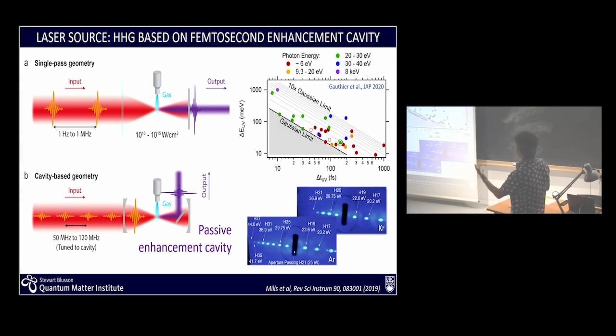The key, of course, as I said, is energy versus time resolution. Here you see a nice collection of results in a review paper from ZX Shen's group, and you see that the limit is basically the Gaussian limit, set by Heisenberg, how much you can push one versus the other. And when you go to high photon energy, so for instance in green here, 20 to 30 electron volts, you see that it's much easier to achieve the limit if you're really pushing down the time. So you're making your pulses very compressed, but now you lose the energy resolution. And so that's where we are.